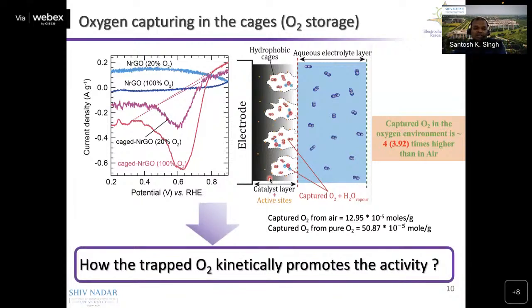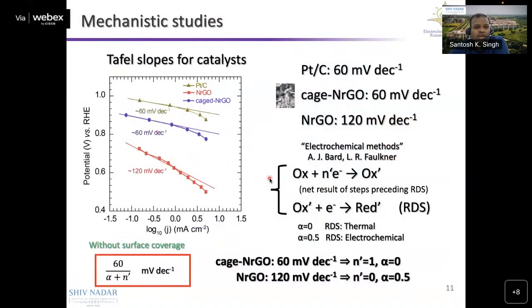Next comes the question: if oxygen is captured in the cages, how does it kinetically promote the ORR activity? To confirm that, we did some mechanistic studies and calculated the Tafel slope of these two catalysts, hydrophilic and hydrophobic. The hydrophilic one shows 120 millivolt per decade, and the hydrophobic one shows 60 millivolt per decade. This means that if the Tafel slope is different, it is following a different RDS step for this reaction.